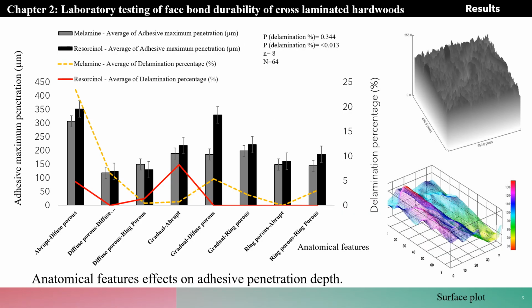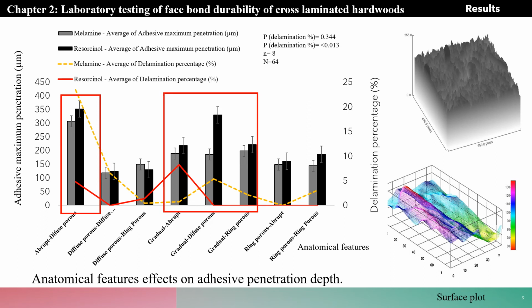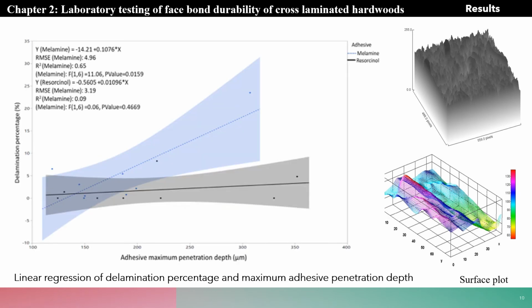So from here, we can see from the results that species like abrupt diffuse porous, gradual abrupt, and gradual diffuse porous and gradual ring porous tend to have relatively higher penetration compared to the other type of combinations.